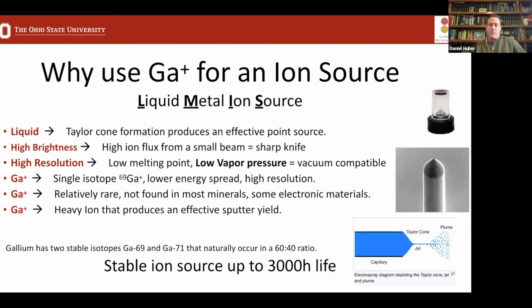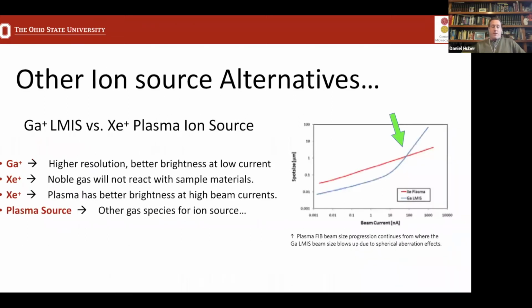Second of all, the reservoir of gallium behind the needle is supplying the source. It's got a significant reservoir of gallium there, so you can actually have a source that will give you up to 3,000 hours of lifetime. There are some other alternatives for ion sources. Gallium, like I said, at low currents gives you very good brightness.